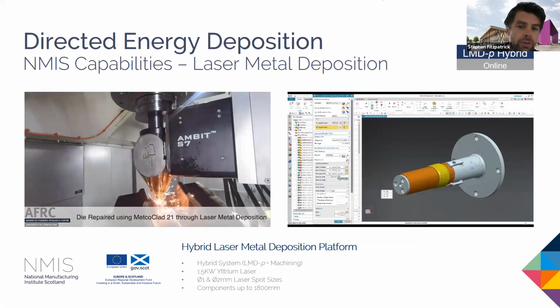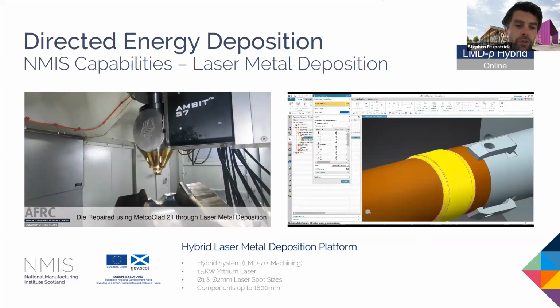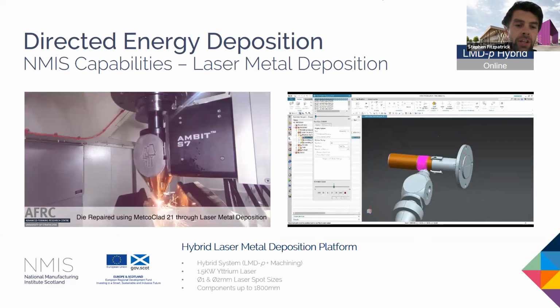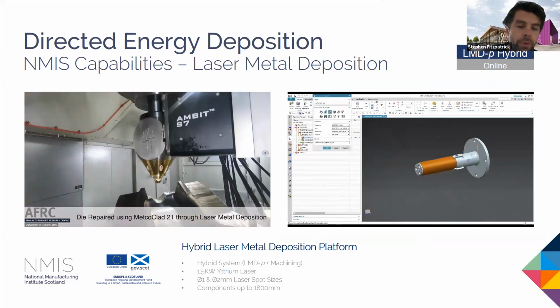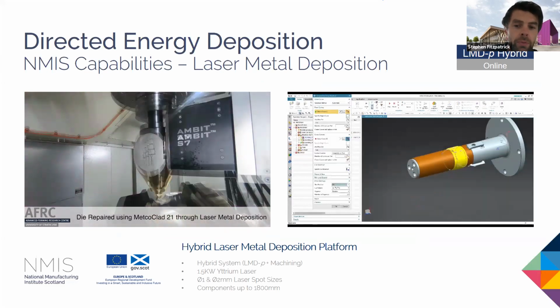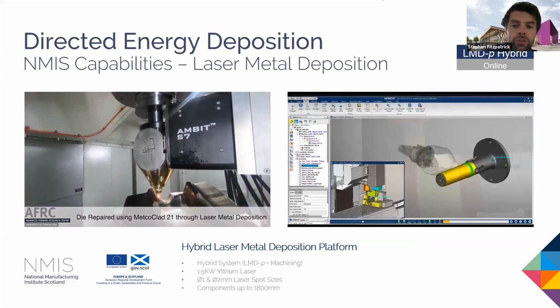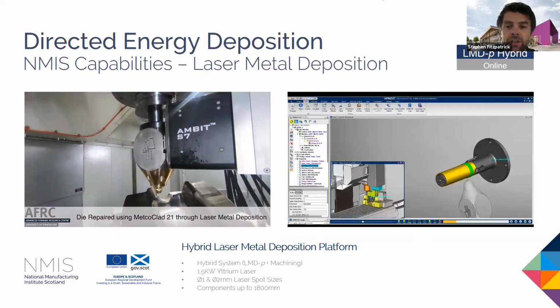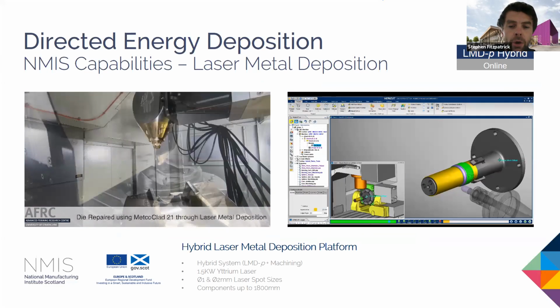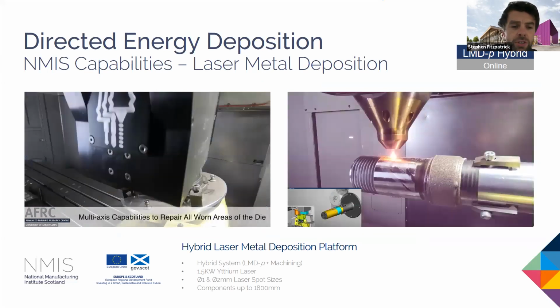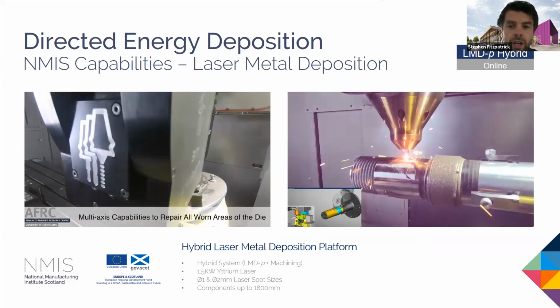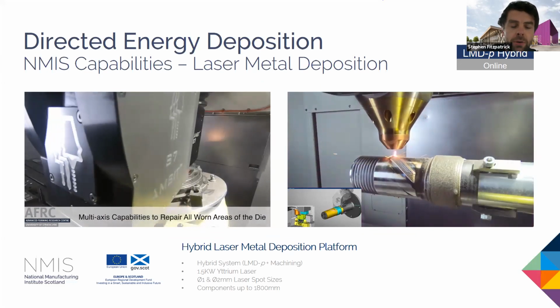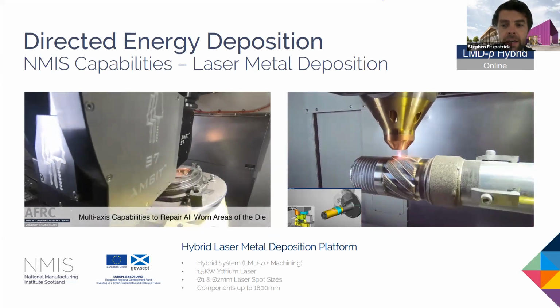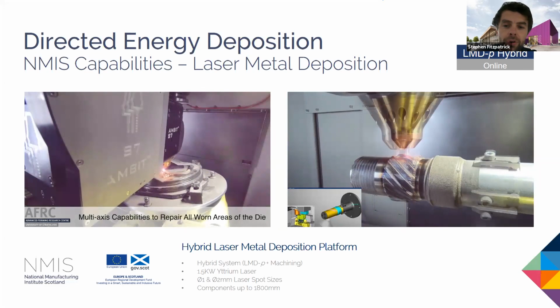And this is our LMD hybrid platform. It is a laser metal deposition machine, but we can also carry out machining on it as well. So powder is blown through the nozzle, and using a laser as an energy source, we can create a melt pool. And it does have some specific benefits over, say, the arc-based processes that I'm going to discuss in a little minute. It's got relatively low heat input.